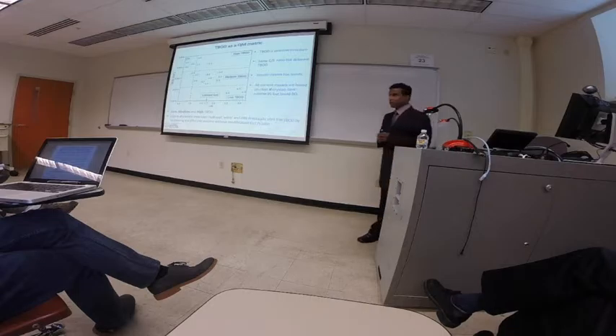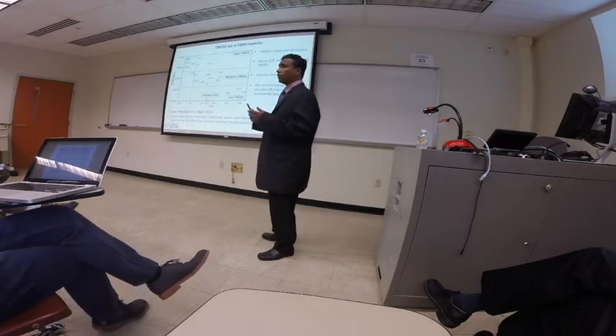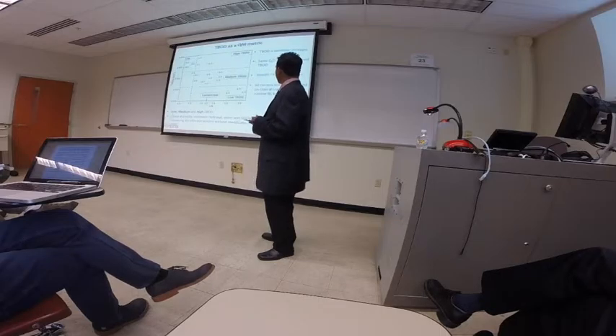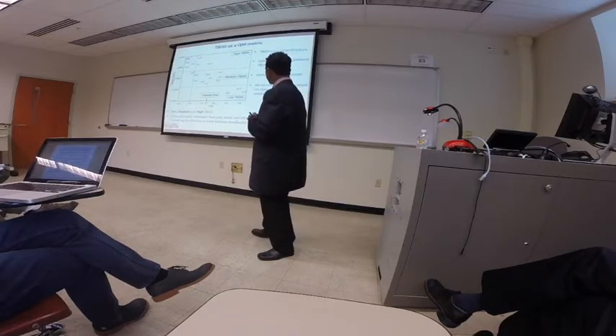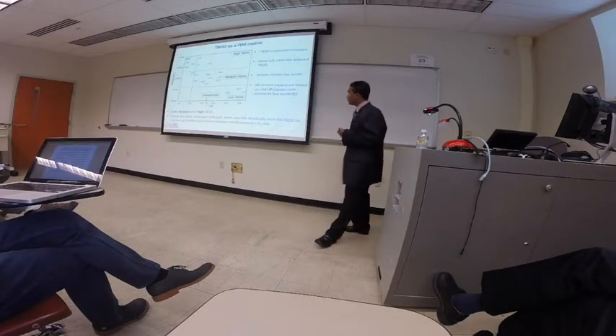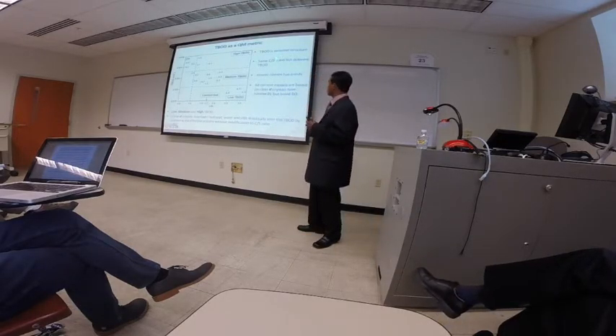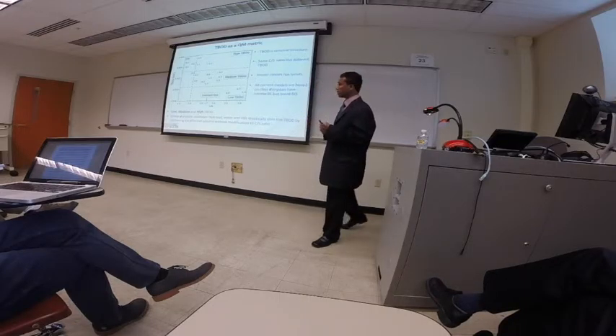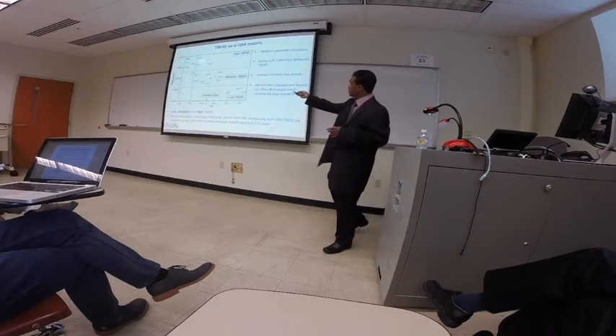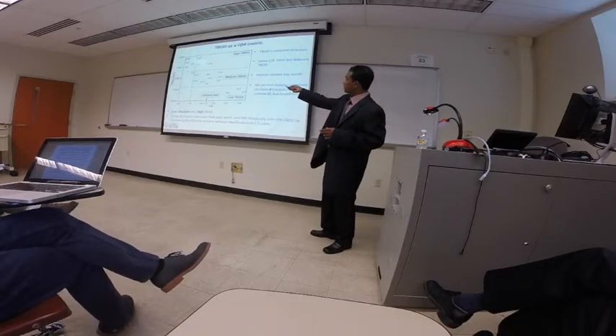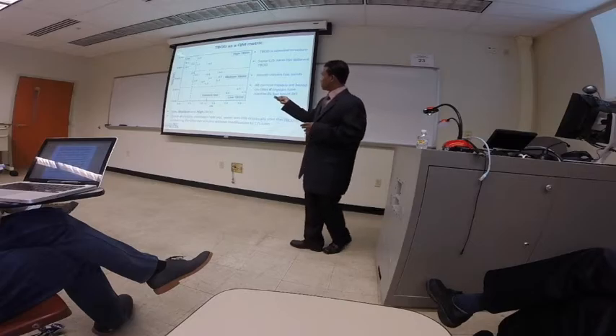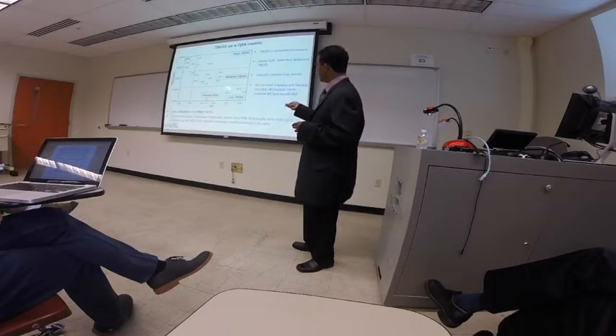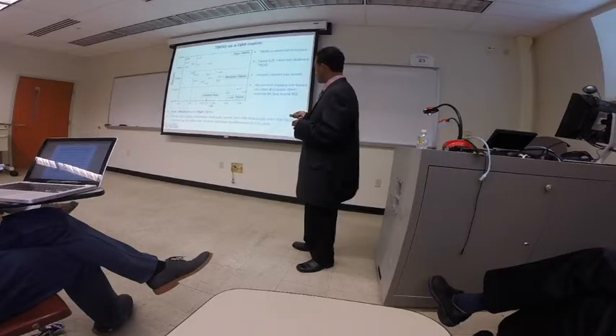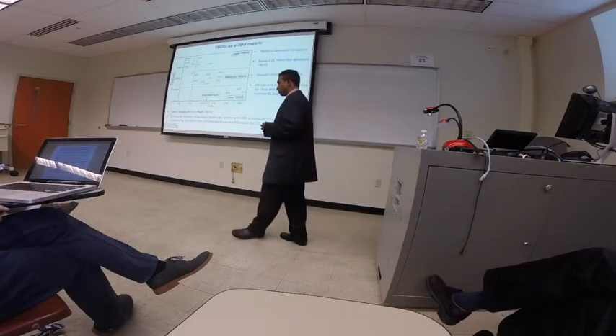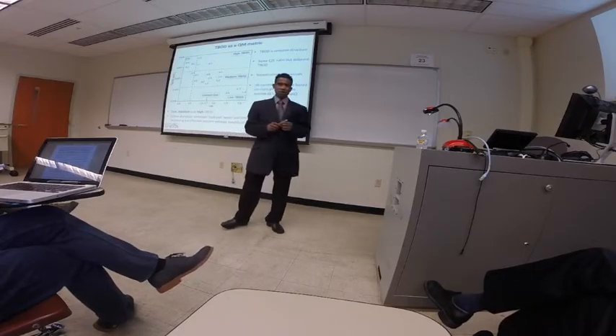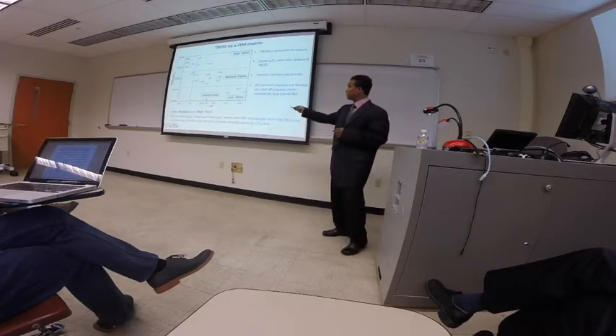Moving on, we plotted the total bond order density as a metric against the traditional C/S ratio to find out any similarities. Well, the first thing you see is that total bond order density is obviously much more sensitive because it's sensitive to the chemistry of the crystal. And for the same C/S ratio, you get a vastly different total bond order density. But in general, the TBOD and C/S ratio have an inverse relationship, which makes sense because when you increase the C/S ratio, you have more calcium ions making more calcium oxide bonds. These are weaker bonds, reducing the TBOD.